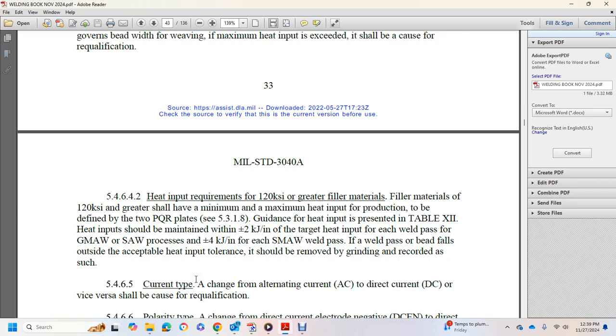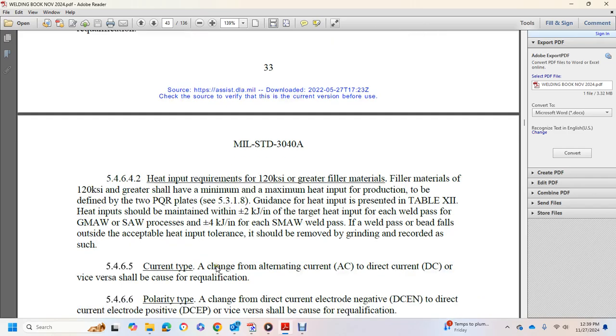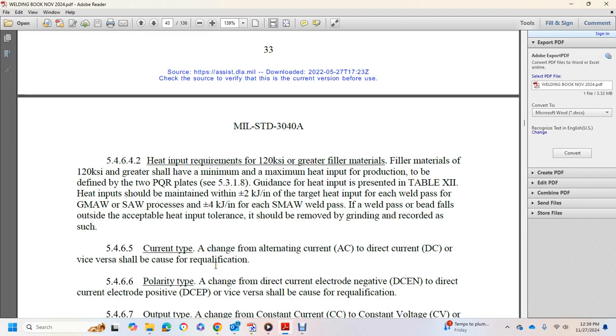Each weld path for gas metal arc and submerged arc welding, plus or minus 4 kJ/inch of shielded metal arc welding pass. Weld pass beads that fall outside the acceptable heat input tolerance should be removed by grinding and recorded as such. Current type change, from alternating current to direct current or vice versa, should call for requalification.